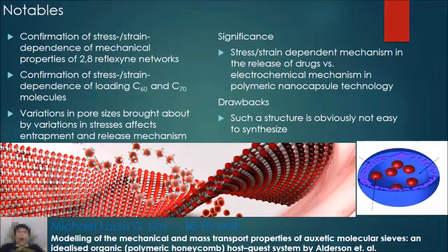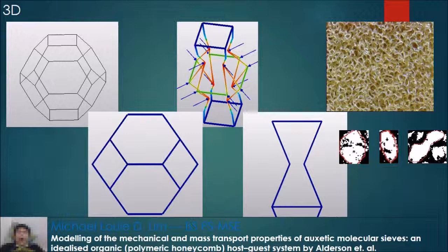However, as can be inferred from the structure of the guest system shown earlier, the auxetic network as studied by the authors of the study is not particularly easy to synthesize because of the degree of order of the polymeric molecules involved. However, foam, despite the randomness of the unit cells, can easily become a template for 3D auxetic guest systems. Foam unit cells can be idealized as tetrakaidecahedron in shape. Auxetic foam cells, therefore,